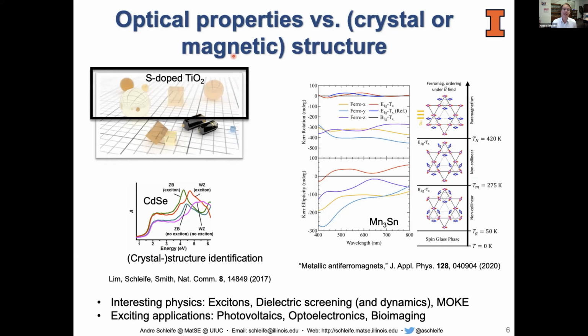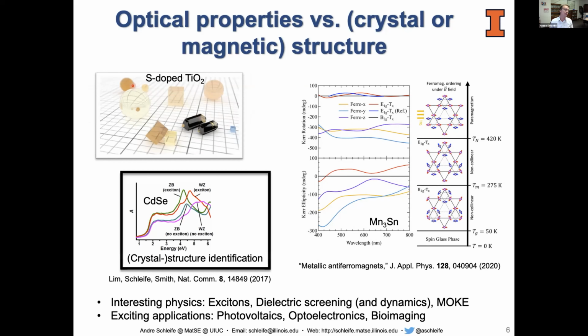So just to walk you through the slide, on the top left, you can see an image that used our first principles data. The image is computer generated, but it used our simulated data for sulfur doped titanium oxide. And as you go from this almost whitish looking sphere to darker and darker, what happened is we increased the amount of sulfur doping in the titanium oxide, and you can see how that affects the optical properties. So in other words, we have a very accurate description that we can obtain with our techniques. And then we use that. I will not walk you through tons of examples because I think that at some point gets boring. I will show you some briefly, and then I'll discuss the limitations of the framework and what we need to do.